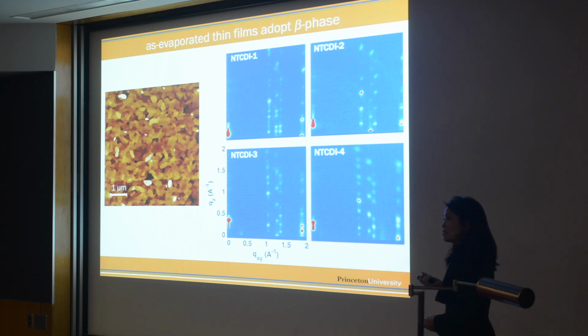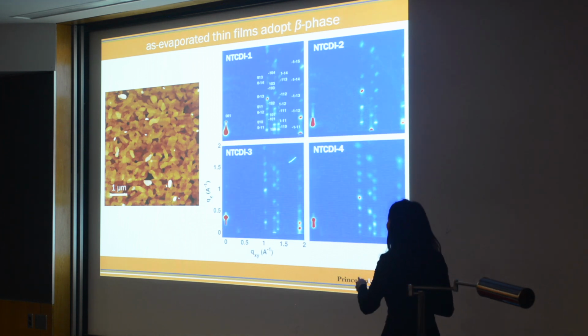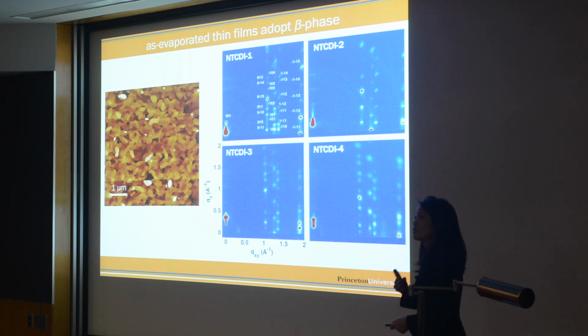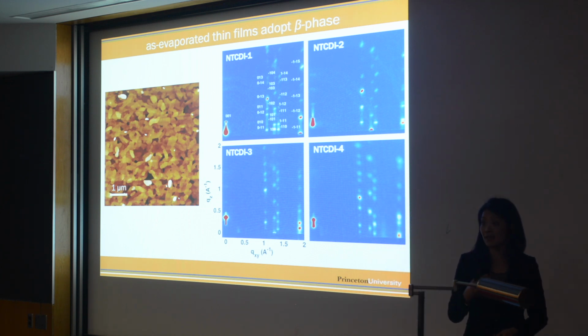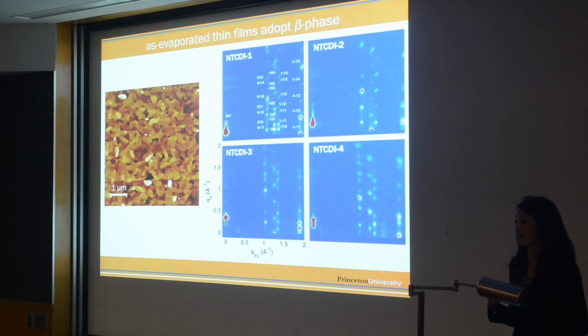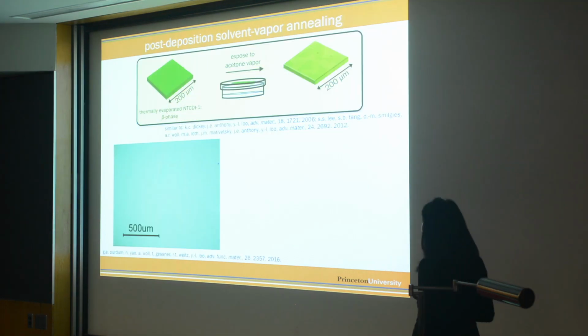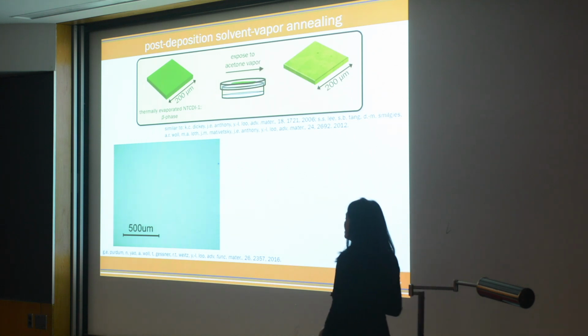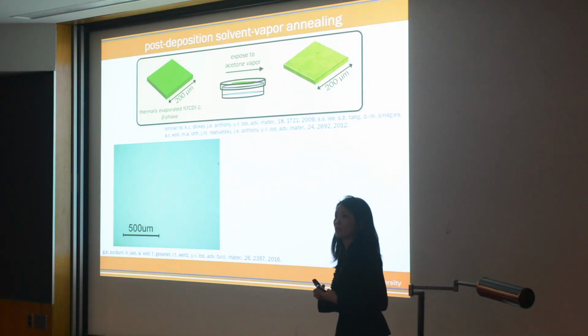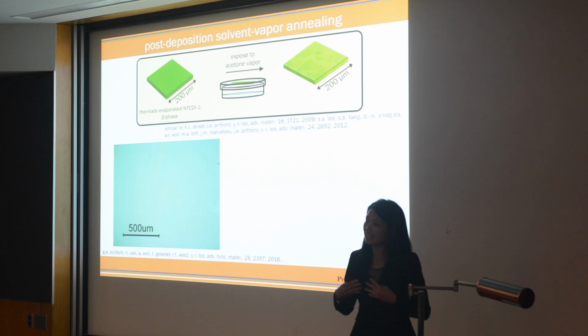Because we have a single crystal structure, we can actually index these spots. And it turns out that if you index these spots, it tells us that all these compounds, when we evaporate them, adopt the beta phase, the two-dimensional pi stacking motif. Okay? They all adopt the beta phase. In our lab, what we like to do is do this post-deposition processing to either anneal the film so that we can increase the crystallinity.